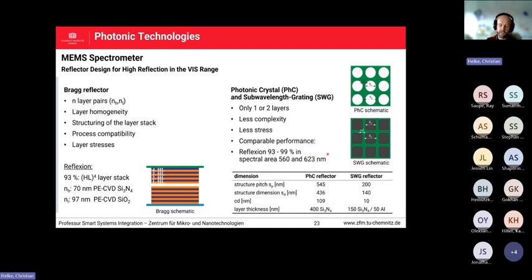And in this project, we investigated two different concepts. One is the metals on membrane concept. We call it the sub-wavelength grating scheme. And the other one is the nanostructured silicon nitride membrane itself. We call it the photonic crystal scheme. The dimensions shown here below for the photonic crystal reflector itself are 436 nanometer holes with, let's say, 100 nanometers in between. And for the sub-wavelength grating reflector, the metal patches consist of 50 nanometer aluminum with a width of 140 nanometers and a pitch of 200 nanometers.